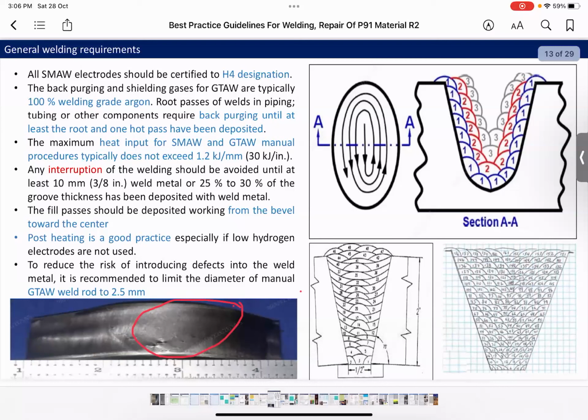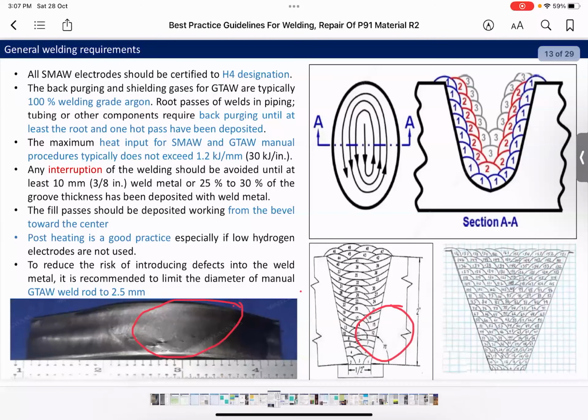For the size or the angle of the bevel, it should be 10 to 15 degrees as shown here. We'll see later on in the slides how this angle can affect the service life of the weld joint. So the common practice we follow of 37 degrees or so can adversely impact the service life of P91 material. And as I said, the bead sequence should be from the bevel to the center of the weld. This is for both weld repair and new bevel.